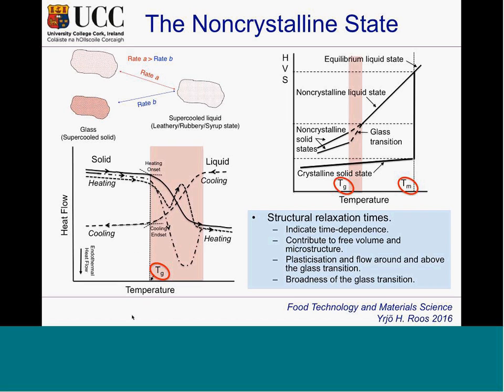The molecules are frozen. They cannot move anywhere. But when we come to the glass transition area, we're in plasticization, thermal and water plasticization, molecules move away from each other, and it becomes more flexible. At the same time, they reorganize, and that releases heat. So it requires heat, depending on the state. So they can expand to get to the sort of more equilibrium state of the molecules. They need more energy for that. If we have rapid cooling and slow heating, we would see an exotherm, because the molecules can release the extra energy. And we describe all those phenomena by looking at rapid or slow cooling, and we can get different glass states.